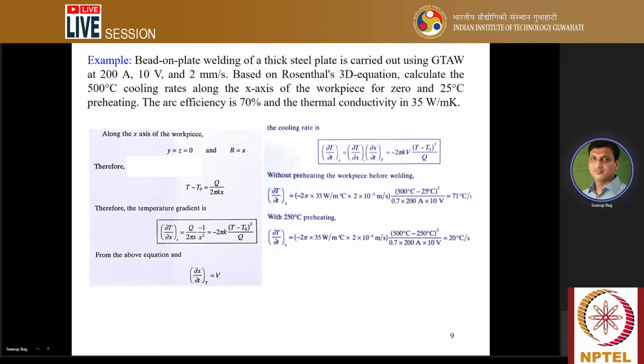Now, if someone asks for a numerical, I just picked up one numerical from a standard book. Just look at the example. We are considering bead-on-plate welding. That means simply heating the substrate material, a thick steel plate, using the arc, carried out with the gas tungsten arc welding process at 200 ampere, 10 volt, and the welding speed is 2 millimeter per second. Now, based on Rosenthal's 3D equation, calculate the 500 degree centigrade cooling rates along the x-axis of the workpiece for 0 and 25 degree centigrade.